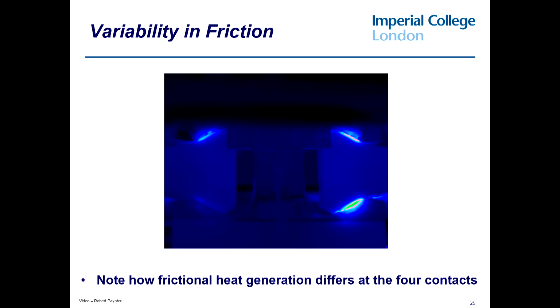So even with four notionally identical contacts, you get very, very different behavior. And small differences in friction can make a very big difference. For example, it's quite clear that this one is stuck and this one is sliding. If the friction had been slightly the other way around, it would have changed that result.